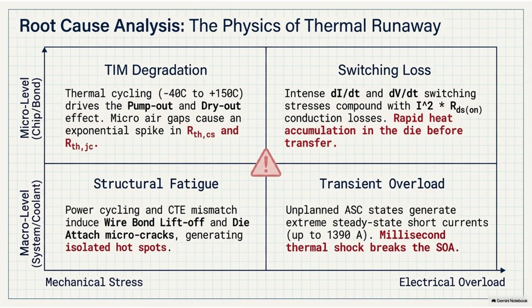But the degradation isn't just happening at the paste layer, right? The actual metallic connections inside the chips start tearing themselves apart. That brings us to the third physical root cause of a meltdown. Wire bond and die attach fatigue. We just discussed the CTE mismatch, warping the heavy base plates, but that same differential expansion is happening on the microscopic scale on top of the chip.